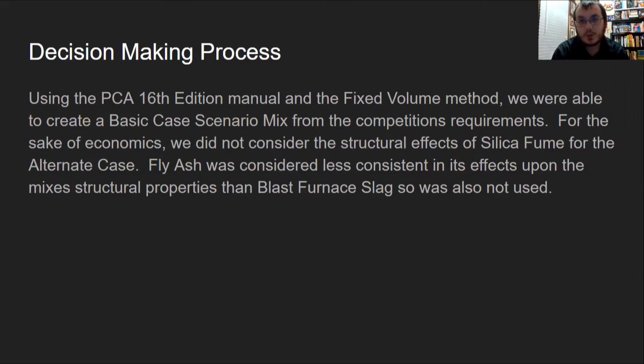For the sake of economics, we decided not to consider silica fume due to its considerably greater cost relative to cement. Further, we were hesitant in using fly ash due to being unable to fully replace the allowed amount, in addition to some concerns with getting consistent results with it from what we were able to read. As a result, our alternate mixture uses solely blast furnace slag.